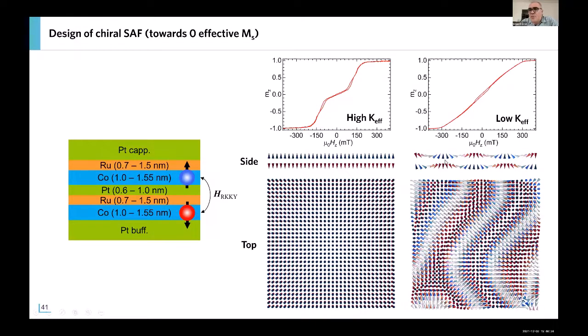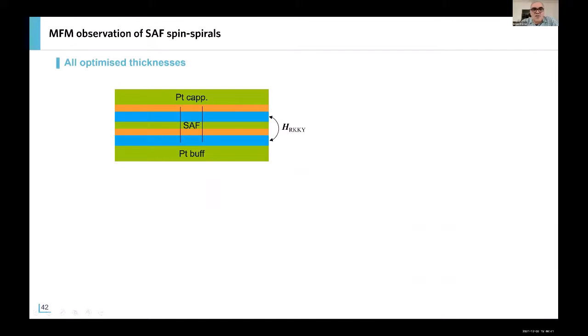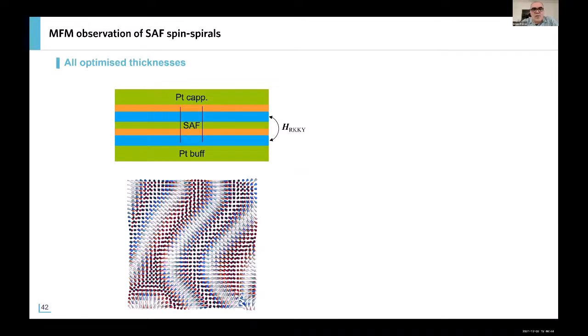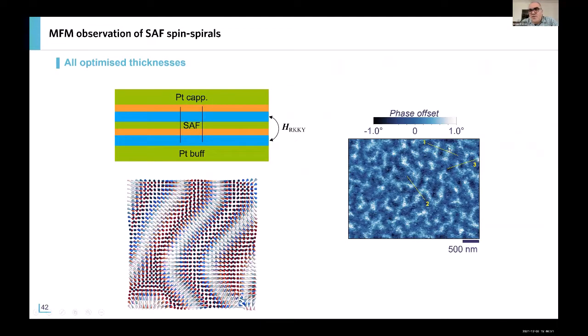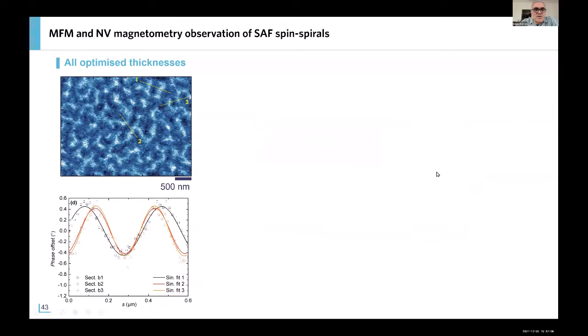What happens if you have now a compensated effective anisotropy? In fact, the combination of the Dzyaloshinskii-Moriya interaction and the absence of coupling of long-range dipolar fields creates a spin spiral state. Okay, and in fact, this is what we try to demonstrate experimentally first. So we prepare a system with two strongly coupled antiferromagnetic layers with compensated anisotropy. And this is the top view of the configuration recorded by vacuum MFM, because the magnetic signal is extremely weak. Again, at each position, we do have an antiferromagnetic coupling, but you do see here that we have this spin spiral state.